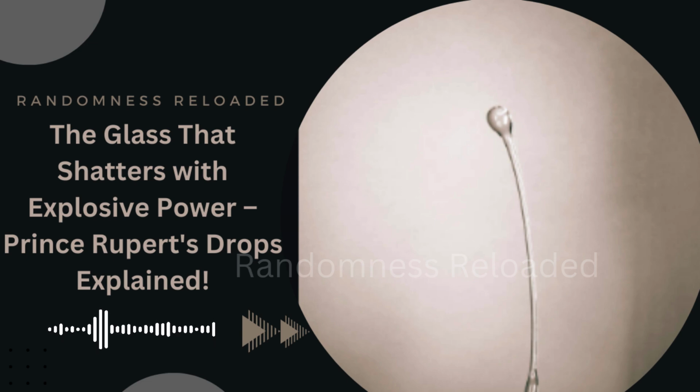Remind me about those patterns again. Okay, so fragments from the outer layer, the part under the most compression, were typically very thin and flat, almost like little plates. Like safety glass shattering into those flat shards. Exactly. Those plate-like fragments are a direct result of the compressive forces acting on the glass. Gotcha. But the fragments from the inner part of the drop, the area under tension, are more blocky and irregular. Like those jumbled dice we were talking about earlier.